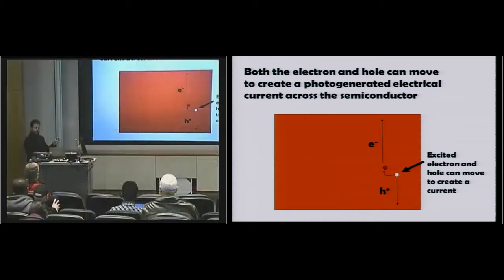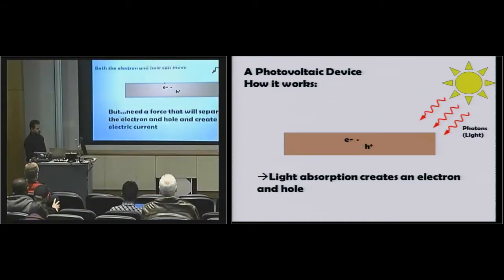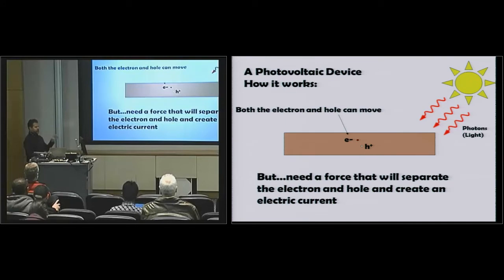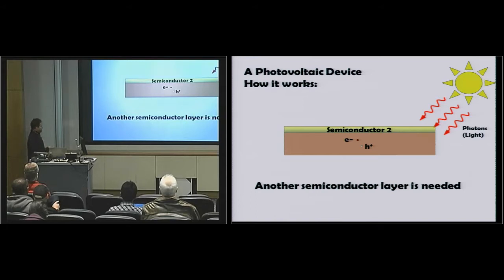So you have to have the absorber, but then you need this junction. There has to be some driving force to separate the electron and hole, and if there's not, you form the electron-hole pair and they just recombine, and you lose that energy. So you have one semiconductor that's primarily the light absorber. Then you have a second semiconductor that creates a built-in electric potential. In the case of silicon, you can have silicon that's doped with an impurity that gives rise to an excess of electrons on one side and an excess of holes on the other.